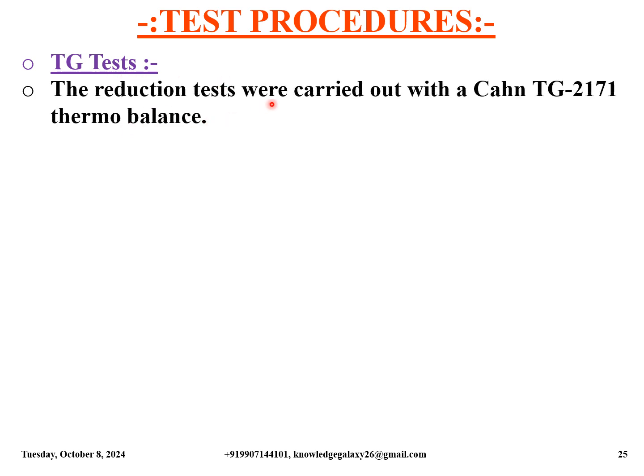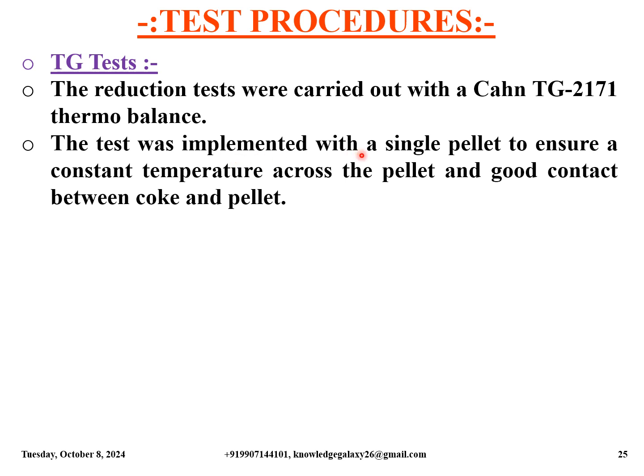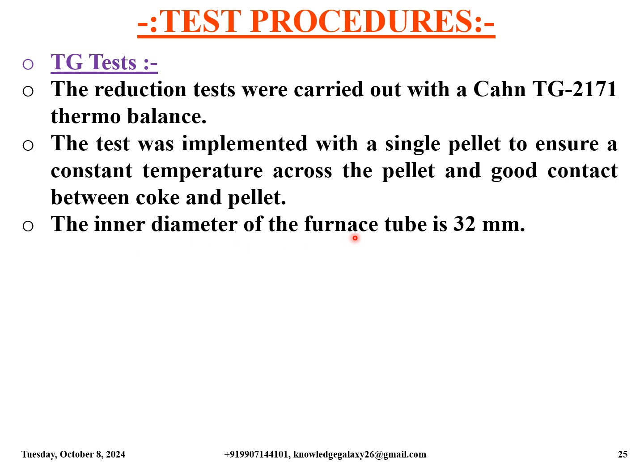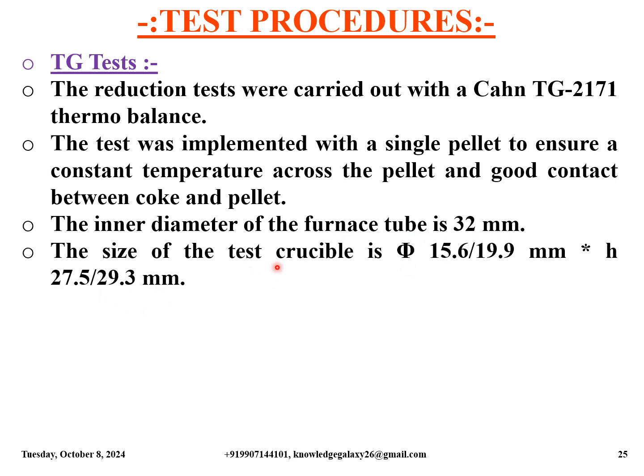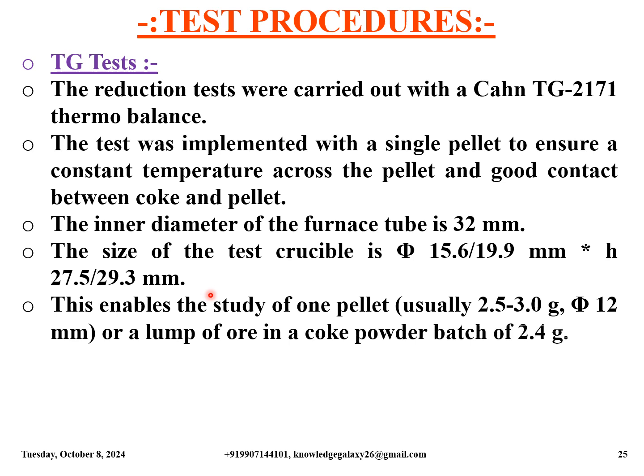Now let us discuss the test procedures. First, let us discuss the TG tests. The reduction tests were carried out with a CAHN TG2171 thermal balance. The test was implemented with a single pellet to ensure a constant temperature across the pellet and good contact between coke and pellet. The inner diameter of the furnace tube is 32 mm. The size of the test crucible is 15.6 mm inner diameter, that is 19.9 mm outer, and height is 27.5 to 29.3 mm. This enables the study of one pellet, usually of 2.5 to 3 gram of diameter 12 mm, or a lump of ore in a coke powder batch of 2.4 gram.